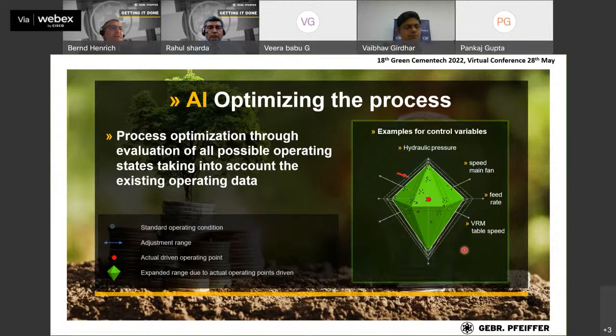And if you have 4 or 5 variables, you might change one of them and look for a little bit of influence. The beauty of using artificial intelligence rules is that once we get the freedom to vary the parameters, there could be operation conditions related to the fan flow, related to the speed of the grinding table when you have a variable speed drive, related to the feed rate and things, which nobody has thought about.